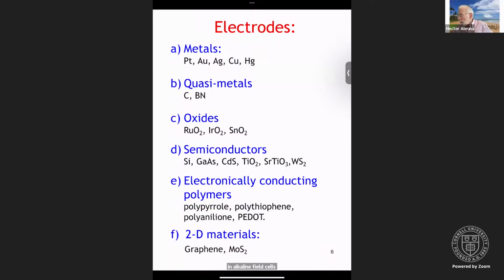In terms of electrodes, there's a variety of materials. Most common ones being metals. So you have things like platinum, gold, silver, and copper. What's common to all of these guys is that these are FCC metals. And so if you know the structure of one, you know the structure of all of them. We'll see later on that there's great value in doing electrochemistry where you can control the symmetry or the geometry of the surface. The most common ones, 111, 100, and 110, the low index faces, can have dramatically different activities.